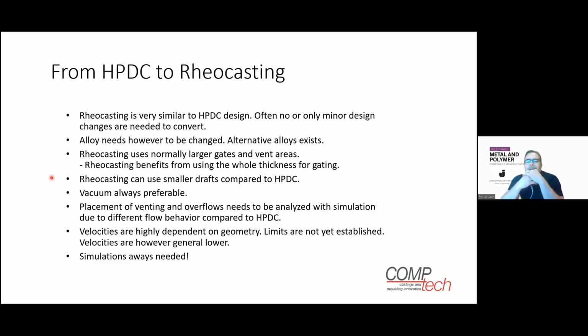We have seen that since we solidify a majority of the material outside the cavity, we have less shrinkage force inside the cavity, which means we can apply smaller drafts if needed compared to high pressure die casting. In these types of castings, I would say that vacuum is always preferable in order to get rid of the entrapped gas.